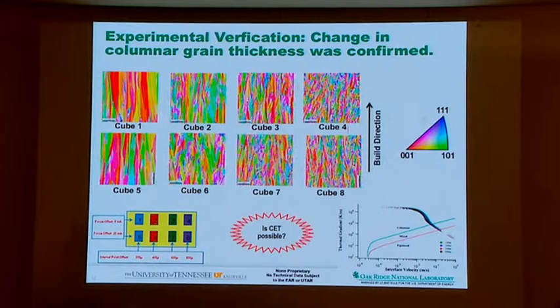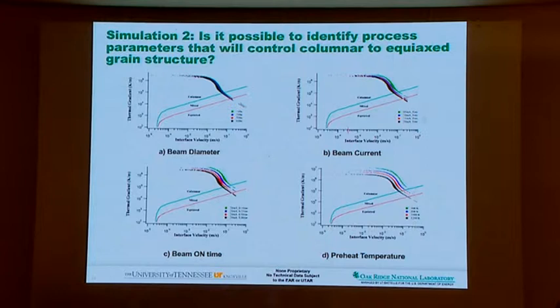He did more experiments, and he understood one fundamental concept: the computational model is a tool, but you need to have a concept. So he asked, how can I reduce the thermal gradient further? The way you would do that is to increase the preheat. That means making sure the spot melting occurs with already higher preheat. So he modified the beam scanning strategies. It's similar to increasing your firing rate on the substrate so that you don't see individual spots, and probably make a big melt pool. That is how you can control the thermal gradient.